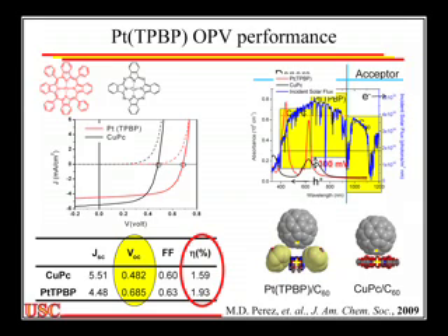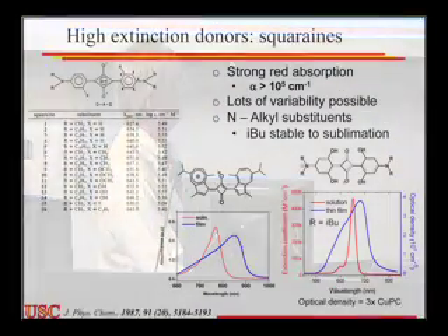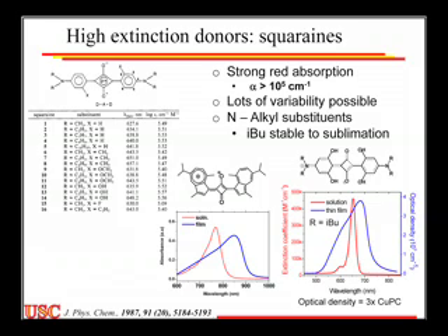You can think of this in the simple Marcus electron transfer argument. The further apart the hole and the electron are, the slower the rate of electron transfer between them. I don't want to go into this, it's another half an hour worth of talk, but we've looked through and modeled this in a number of systems and see the same behavior. Anything we can do to increase the distance at the donor-acceptor interface will increase the open circuit voltage, and will get us to start approaching the upper limit that we see here. That is to say, we can start getting closer to the maximum efficiency if we can push the dark current further out.